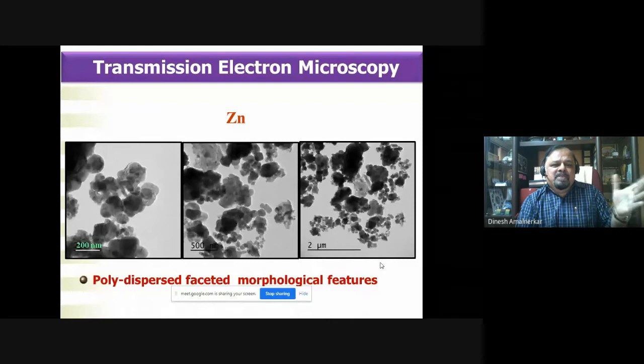oxygen as a major component, though we have not seen formation of any oxide in X-ray diffractograms of either Swarnabhasma or Roupyabhasma. But then when we analyze the TEM data of the Jasadbhasma, we could again see the polydispersity of faceted growth. Faceted growth morphological features is a well-known characteristic of zinc oxide nanomaterials. This is zinc because this just shows that this is Jasadbhasma. It's actually zinc oxide. And again, this electron image, the STEM image, very interesting.